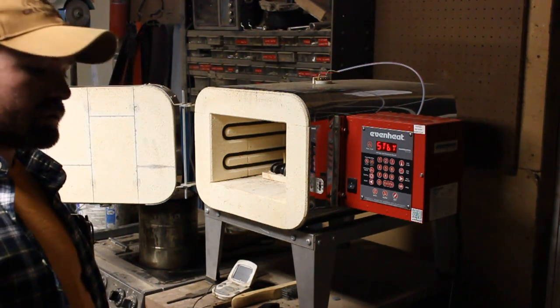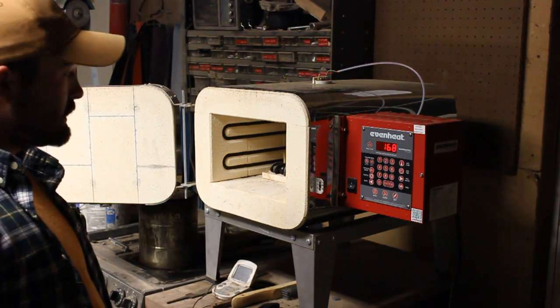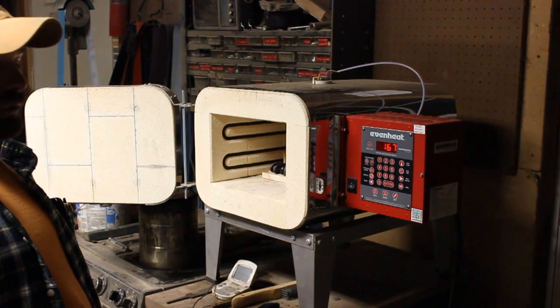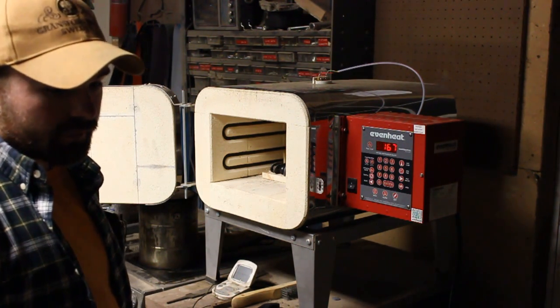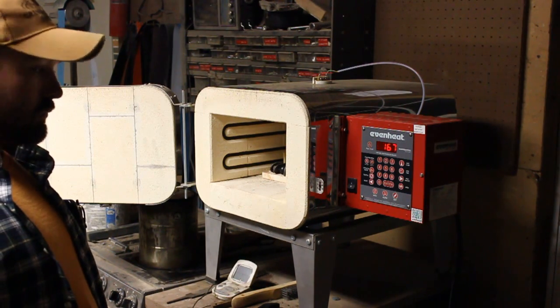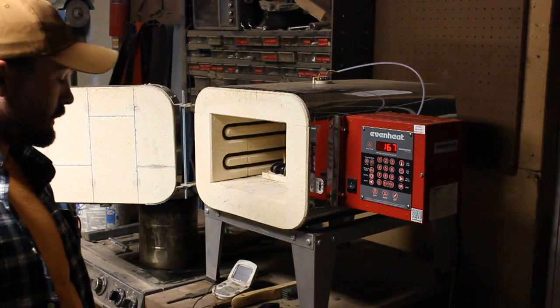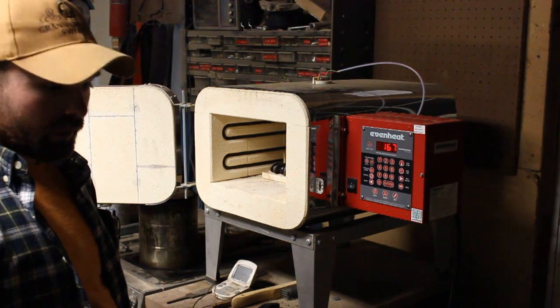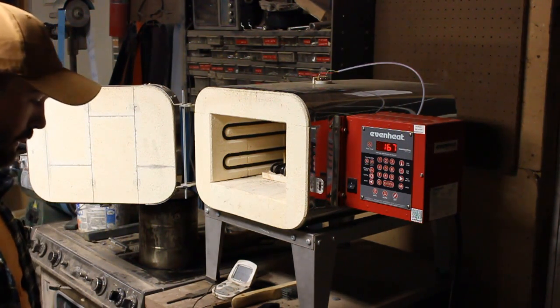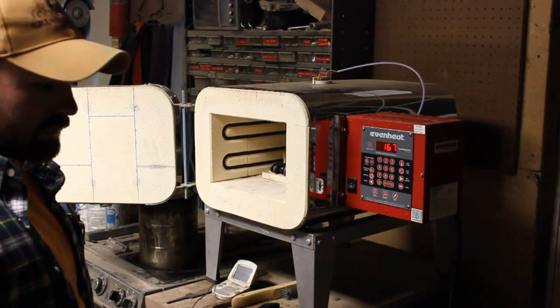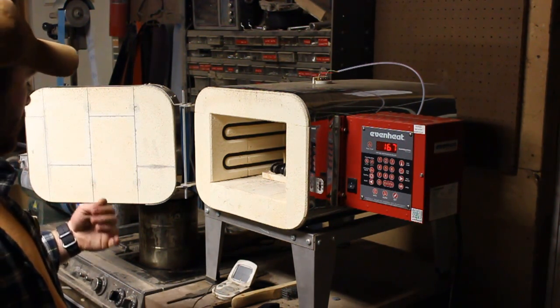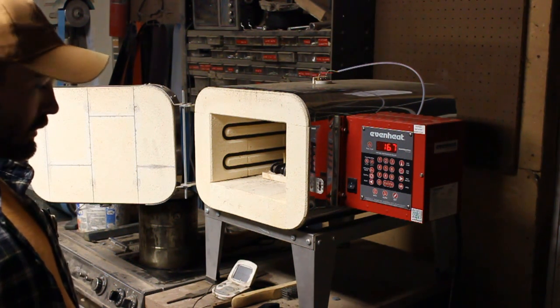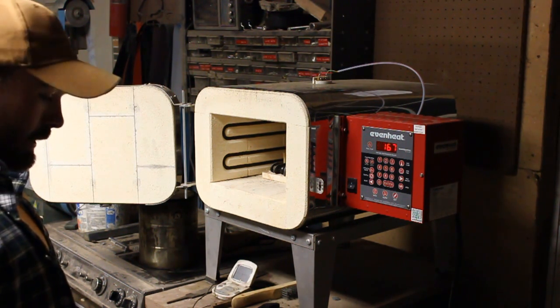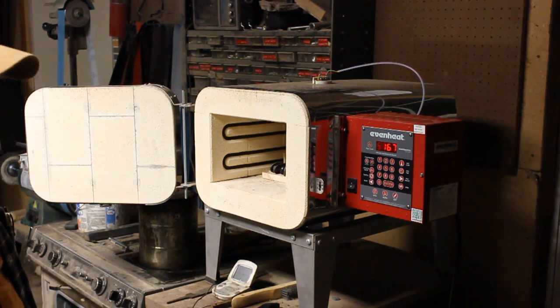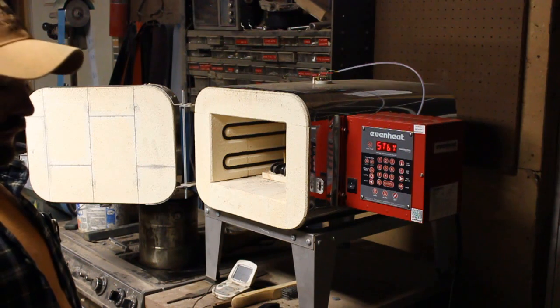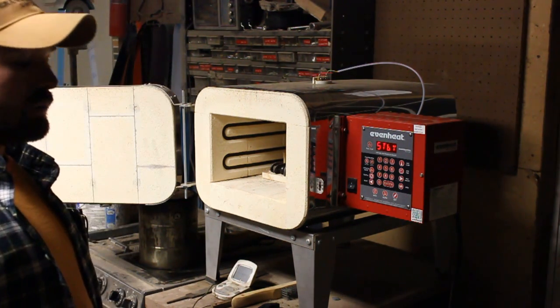So my first tempering cycle, assuming I've done everything right as far as hardening the blades, is 2 hours at 475 degrees Fahrenheit. And what I'll do tonight before I head into the house is I'll shut this up and I'll turn it on, and I'm going to go to bed. And tomorrow morning I'll come back out here and it'll probably be down to the proper temperature. I'll just open it up and check everything out, make sure it's all good to go, and then we'll start up the second cycle, which is 450, 2 hours, let it cool, and then 425, 2 hours, let it cool.